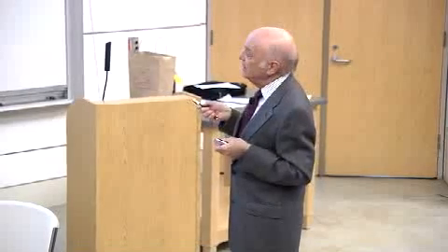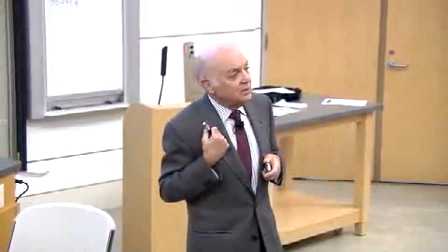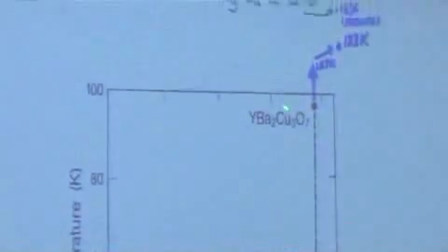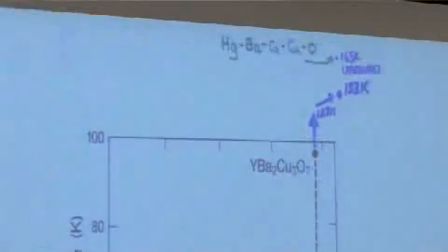And in 1986, 87, some scientists at the IBM laboratory in Switzerland found that copper and oxygen materials, the temperature went way up. So superconductivity was occurring at almost 40 degrees Kelvin. Then people began to squeeze this, and they made another copper oxide material, and it was superconducting up here at almost 100 degrees Kelvin. Now, 77 degrees Kelvin is where nitrogen becomes a liquid. And so you could take liquid nitrogen or liquid air, and you can actually see materials go superconducting. It's still very, very cold compared to room temperature. And in fact, dry ice is at about 195 degrees. And since then, people have been going up slowly. And under pressure, you can get to 165 Kelvin. And there's a very strong effort to try to make these things superconduct at room temperature.